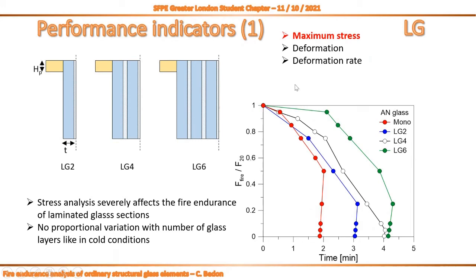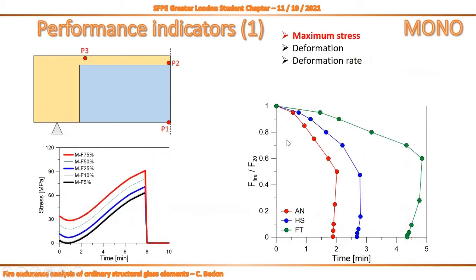For this reason, you can see that some of the dots are overlapped. For example, LG4 and LG6 are mostly identical in presence of fire only, because of F equal to 0. This means that the effect of bending stiffness modification due to temperature only is so strong, even for 4 or 6 glass layers, that our maximum stress peaks are still related to the region in the top corner, like in these contour plots.